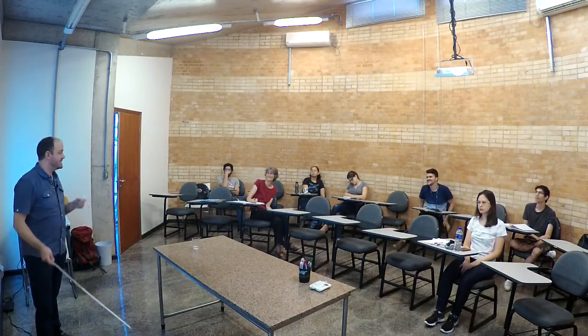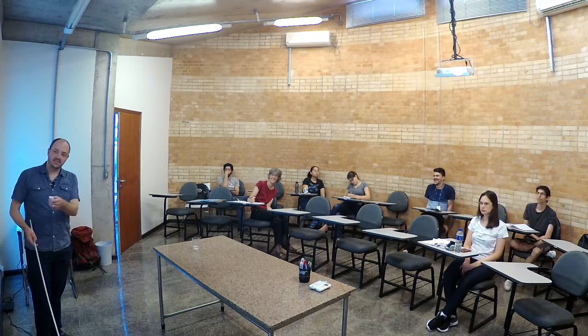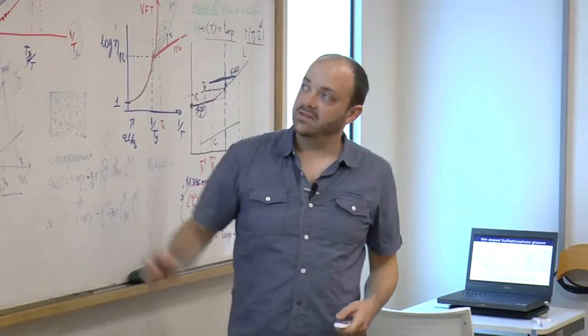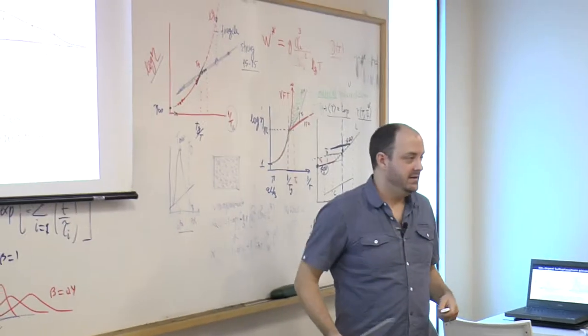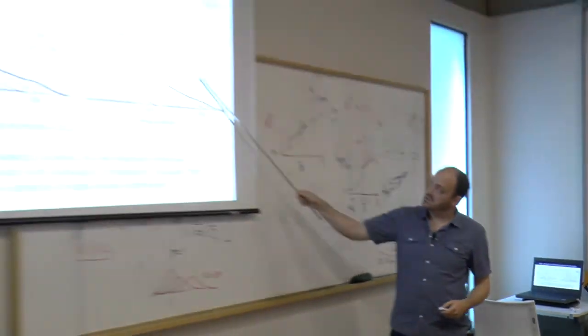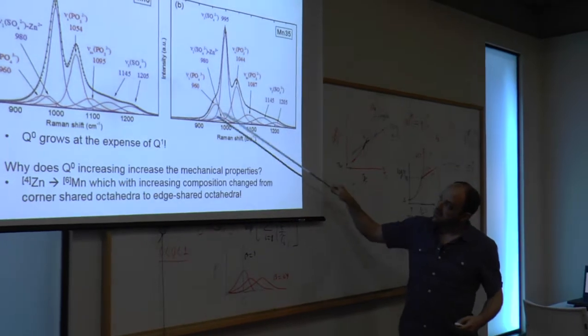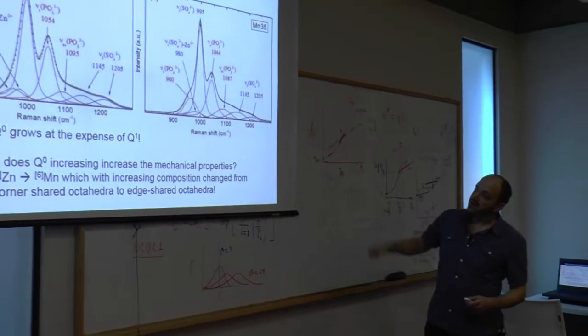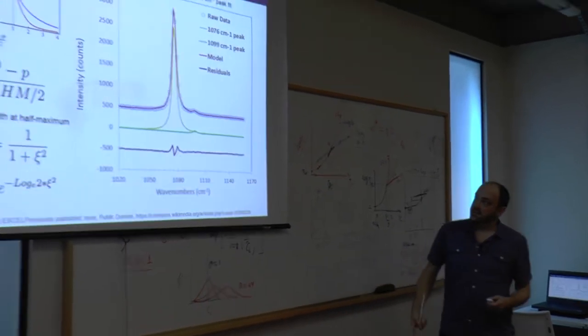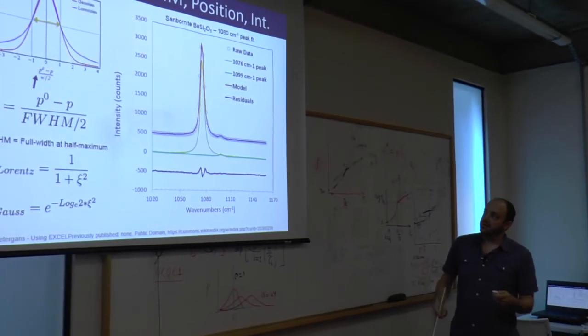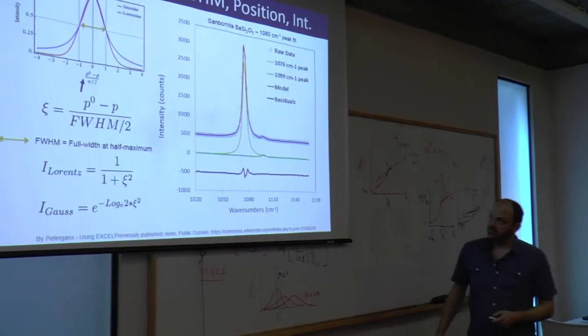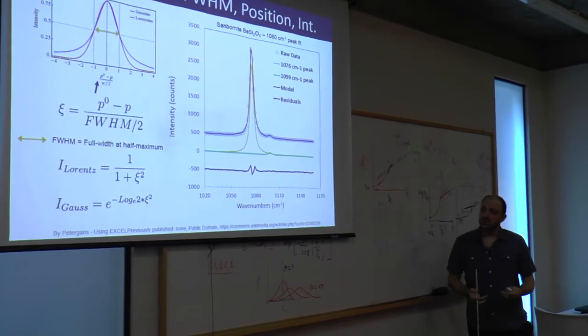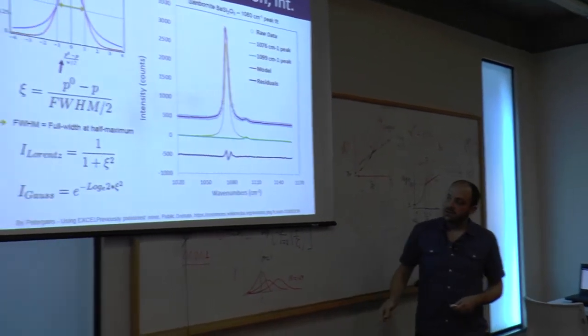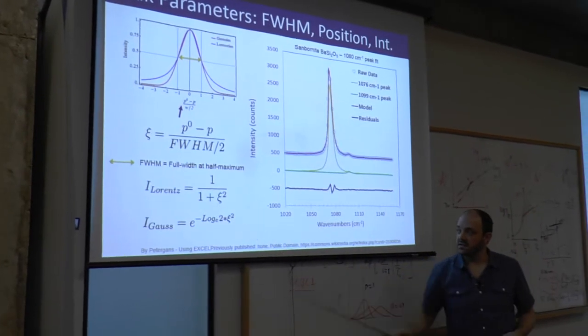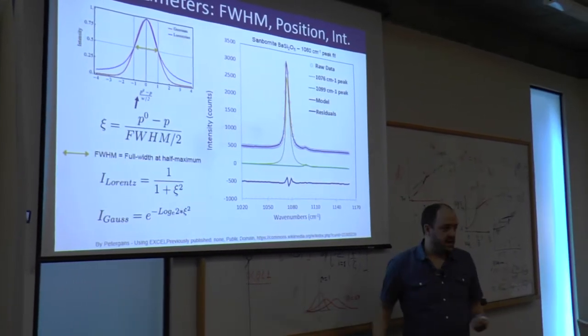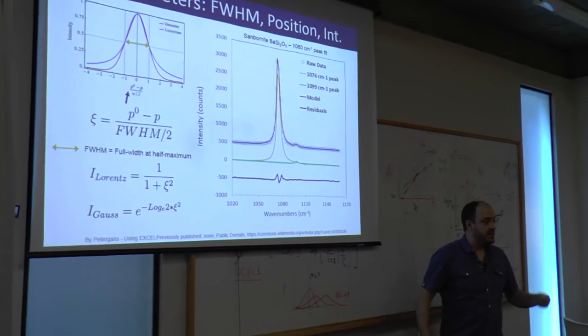So that brings us to the last topic, which is just a couple slides. I'll try not to keep you late, but curve fitting. And you'll see this a lot, and you'll see that we can assign species to all the different vibrations under this spectral envelope. And let's talk about some of the issues. The first is what kind of curves these are. And for crystalline materials, we typically use a Lorentzian line shape, and here's the formula for the intensity of the Lorentzian.